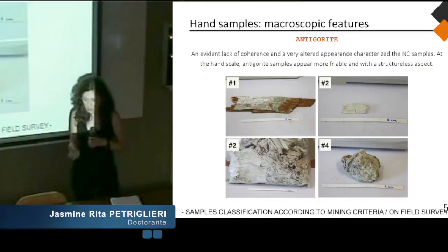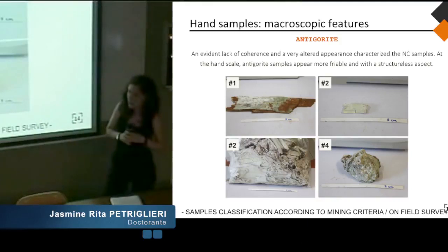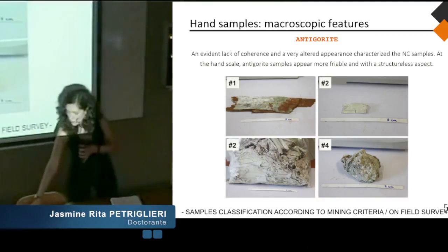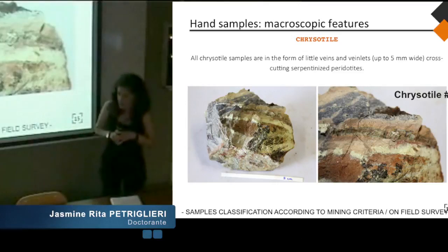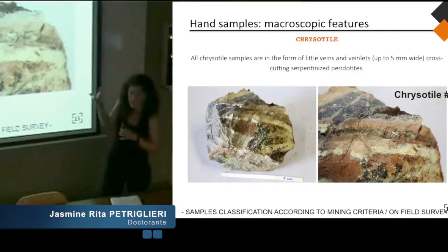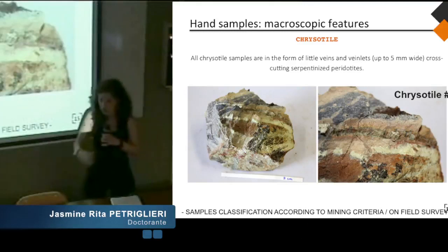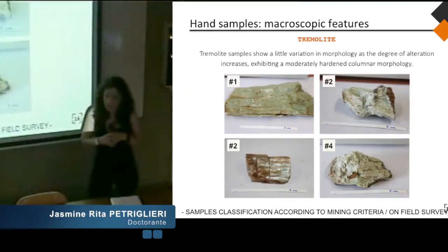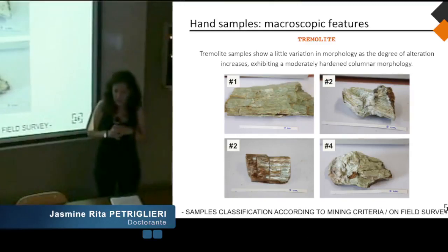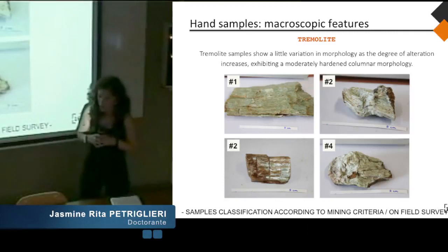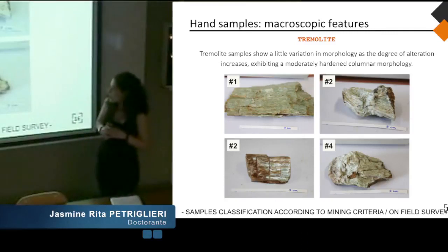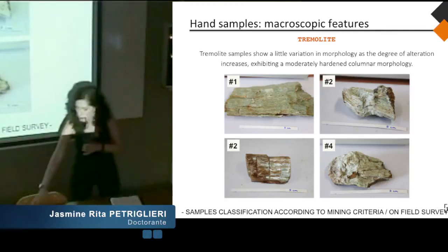Antigorite appears more friable and characterized by a structureless aspect. Chrysotile, instead, appears in the form of little veins and veinlets, cross-cutting the serpentinized peridotite. And this is the typical aspect that we can find at the outcrops of New Caledonia. On the contrary, tremolite samples show little variation in morphology as the degree of alteration increases. Tremolite is characterized by typical columnar morphology.